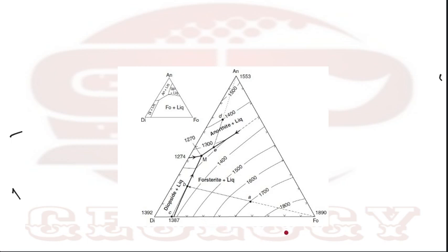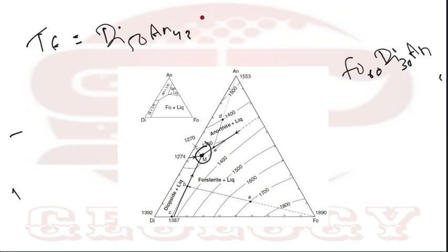Okay, like this, the same thing will go on. The crystallizing behavior, the melting behavior, is just the reverse of the crystallizing behavior. So when we start melting a solid composed of forsterite 60, diopside 30, anorthite 10, the first melt will be produced at what degree and what composition? The first melt will be diopside 50, anorthite 43, forsterite 7 at 1270 degrees Celsius.